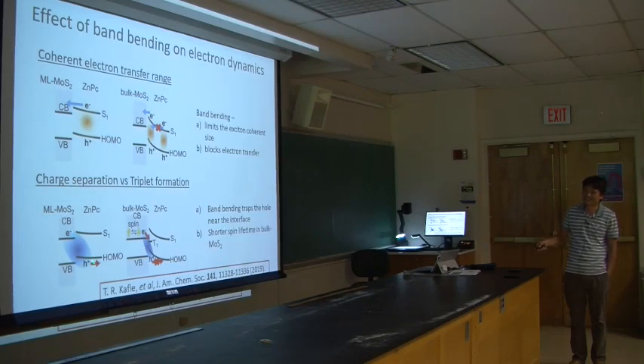So, because of this flatter band, look at the diagram on the bottom here. What we think is we form this CT exciton, so the electron and hole can move away rather easily, without much problem, because of this flatter energy landscape. But for the other interface, we have this huge band bending. So what happens is, if you have this kind of band bending, the electron likes to go that way and the hole likes to go that way, right? Unfortunately for this ZnPc, the hole is on the ZnPc, so it is kind of trapped at the interface.